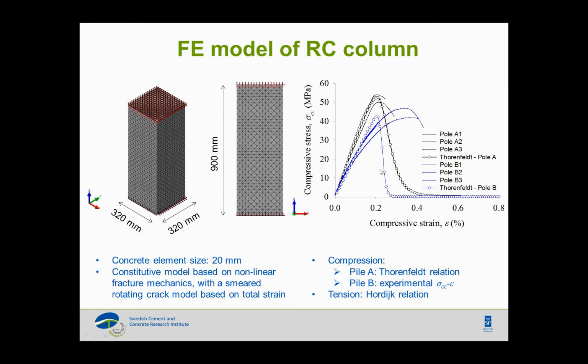What you see here on the right is the compressive stress versus compressive strain. For pile A, which was mildly damaged, the Thorenfeldt curve very much corresponds to what we also saw in these columns. But for pile B, which was severely damaged, the application of the Thorenfeldt curve for compression behavior is not a good option. So we use exactly the same stress-strain curve that we got from the experiments.